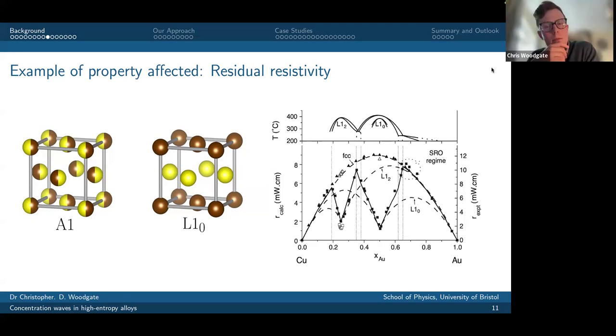Just one point. If the transition is first order, then the correlation length associated with short range order should not actually diverge, but remain finite. Well, indeed, yes. So what is the typical value of the correlation length for this short range order? How short is the order? From experience, you're talking about the first few coordination shells of your lattice. At nearest neighbors there are quite strong pair preferences, maybe at second nearest neighbors there are some pair preferences, but it's not long ranged. It can be, but in general you would expect it to be reasonably short ranged.